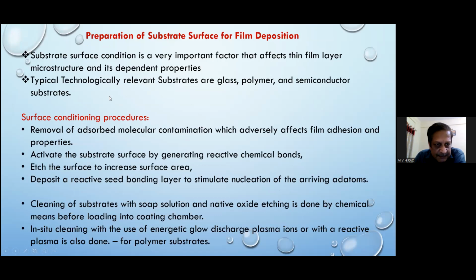And I already mentioned substrate cleanliness is very important. That is normally done by etching and cleaning with soap solution, and then etching chemically if required to have a good surface preparation. Sometimes in situ is possible. In situ means after loading the substrate inside the chamber and getting the vacuum, you create a glow discharge plasma, and these argon ions hit the surface. There is no coating; it will simply knock the surface uniformly, so that any contamination on the surface is removed.